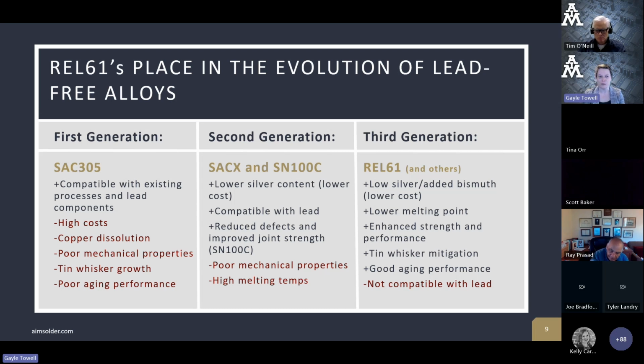So it's sort of paradoxical in a way. Bismuth has this reputation for being brittle, but in smaller percentages, it improves hardness, it can enhance the strength, it improves aging performance, and all sorts of other features of the alloy. So REL61 was essentially we take SAC305, we take out some of the silver, we put in some bismuth, do some other minor adjustments. And what we get is a really great performing alloy in the same space that SAC305 and those types of alloys perform in. It has a slightly lower melting point than SAC305, enhanced strength and performance, reduced tin whiskers. We'll talk about those a little bit later. Really good aging performance. And we've got some really great pictures to show with that.